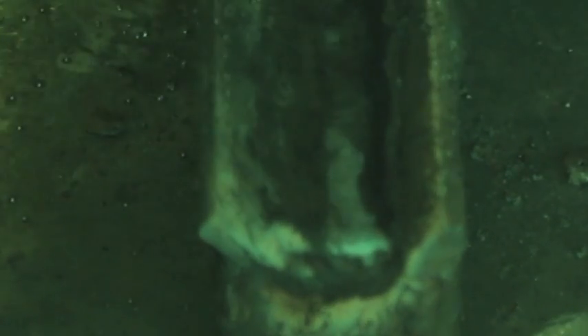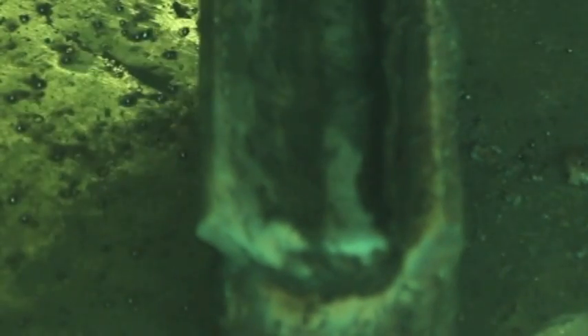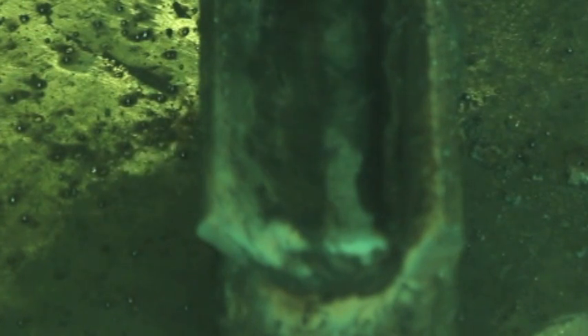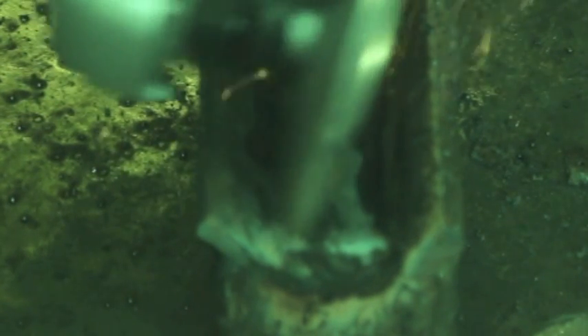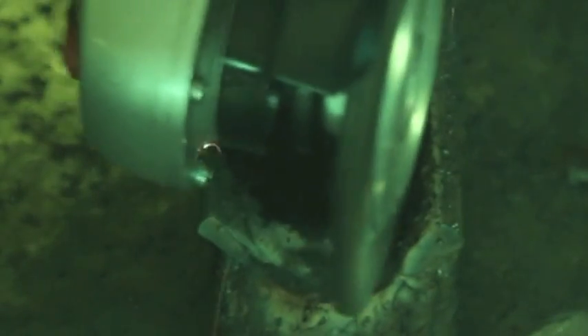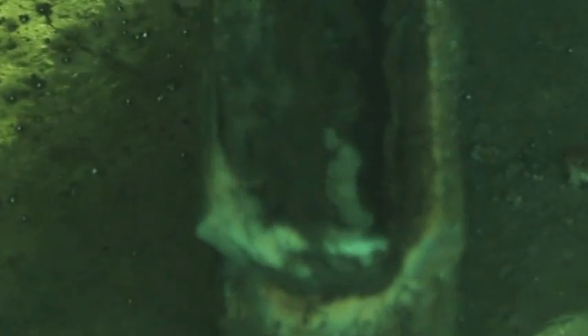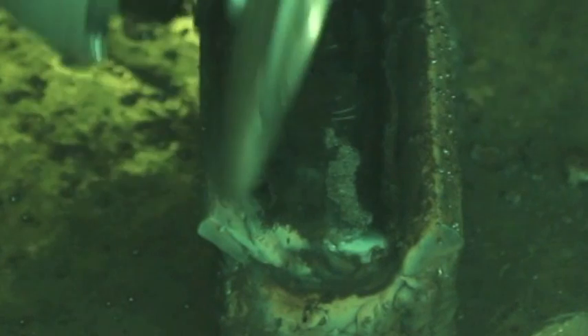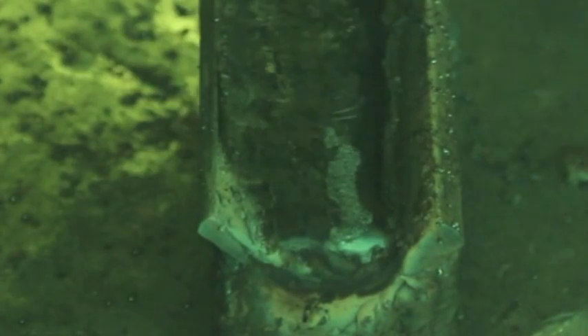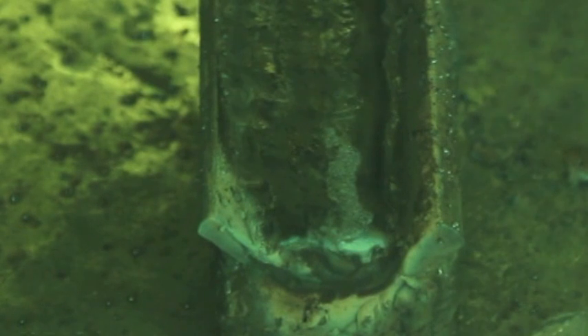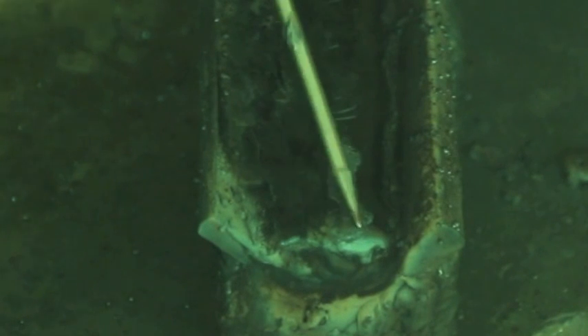Now what happens here, this slag occurs for a bunch of different reasons, but usually the usual culprit here is the fact that the puddle was not allowed to get hot enough, and so it was too cool, too cold. I have to assume that because I move so fast here, that is why this slag stuck. And you won't get this off. I mean, I just hit it with a wire wheel and it just stayed there. You know, you can try to chip it and bang it forever, and it just won't come off.